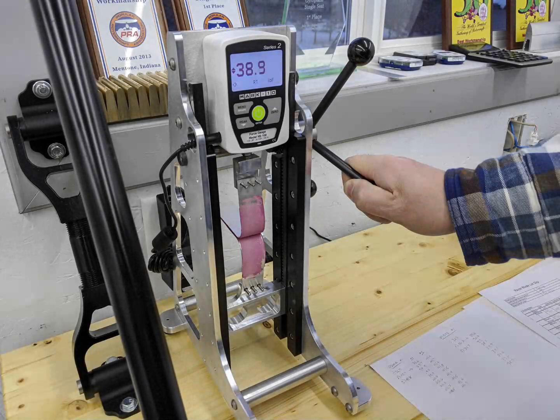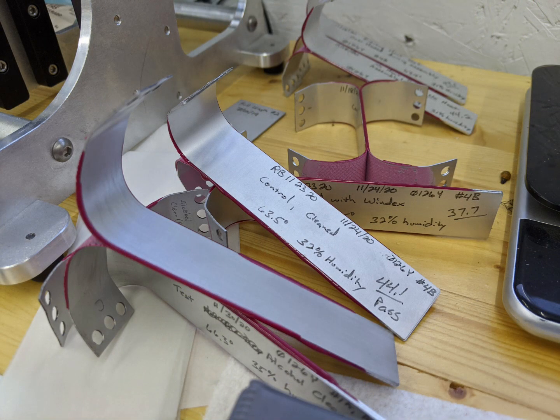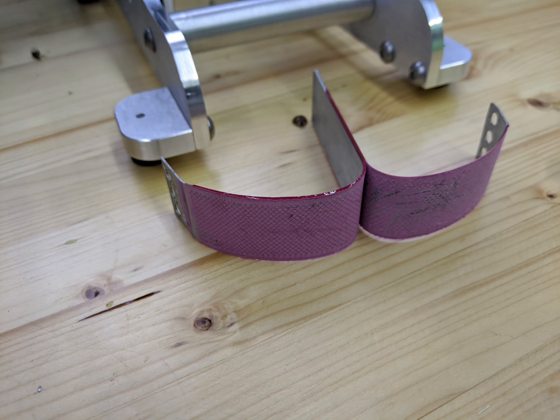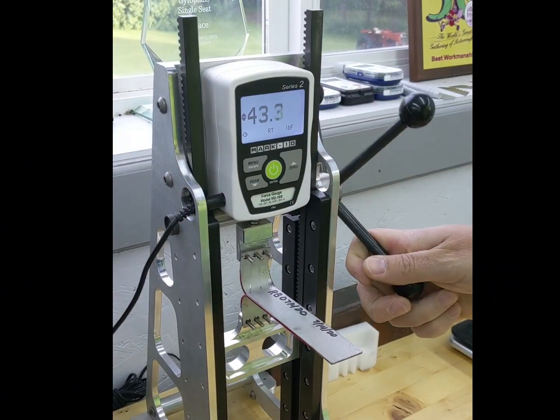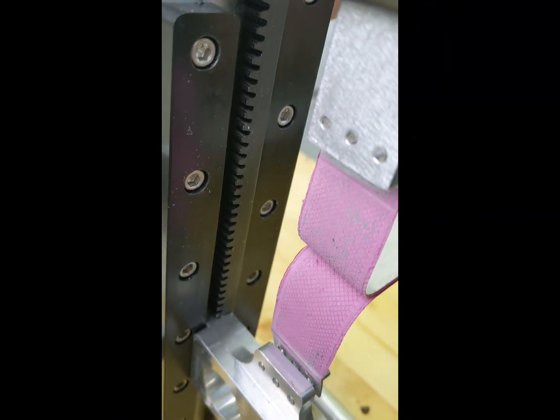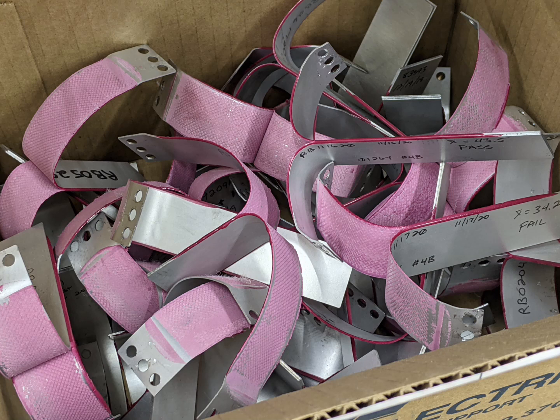As mentioned earlier, a set of coupons is made with the same materials and adhesive and processed in the same etching and cure cycle as the blades. The first process is to check the integrity of these coupons to assure the adhesive is working properly. In a peel test such as this, we are looking for PIW, or pounds per inch of width, for a peel strength of the bond. During this process, we are looking for adhesion and cohesion, meaning the bond of the adhesive to the aluminum base, as well as the adhesive to itself.